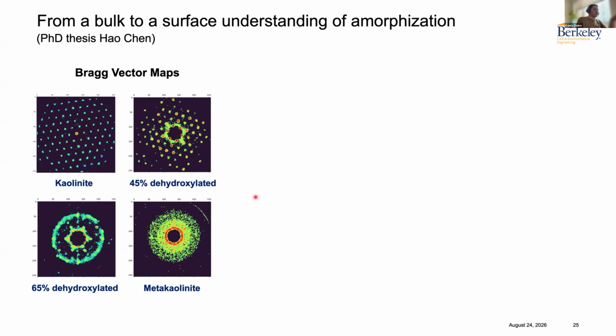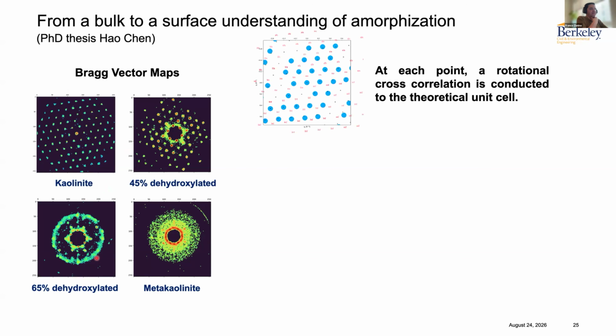Each of these plots contains about 1,000 individual diffraction patterns, and it's a probabilistic representation where red means that there are more pixels on that, and green or blue is less representative. And what we see, as we would expect, is that as we progress in the dehydroxylation and amorphization, we start losing this point pattern that we see for well-ordered kaolinite, and we start seeing something more like a rim pattern, which is evidence of an amorphous material.